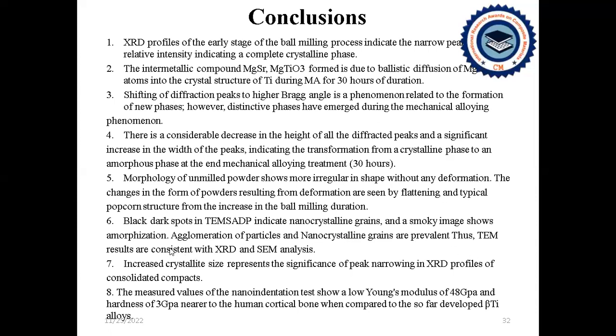and the smoky image suggests that amorphization has taken place, from the crystalline to the amorphous structure, as the transformation has taken place during the ball milling process. And the increased crystallite size represents the significance of the peak narrowing in the XRD profile of the consolidated compact samples. As we all know, during sintering the grain growth will take place, which is suggested by the peak narrowing in the XRD investigation of the compact sample.